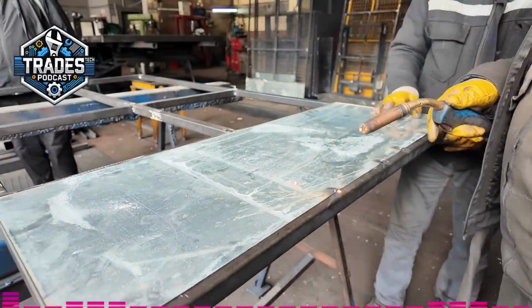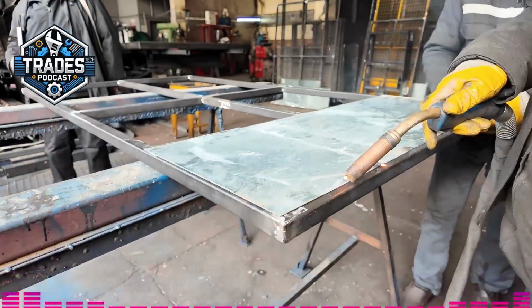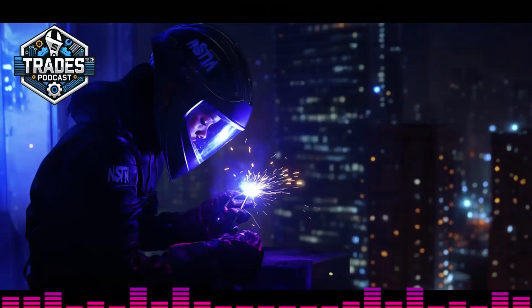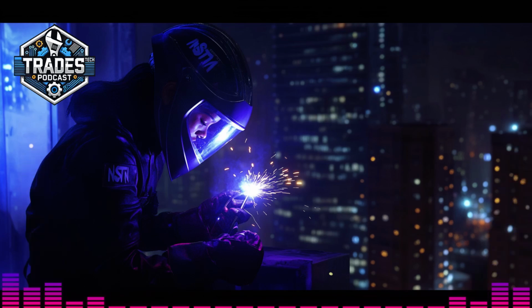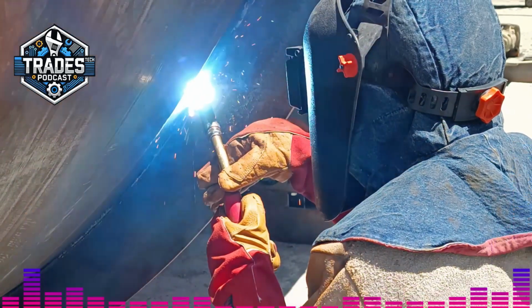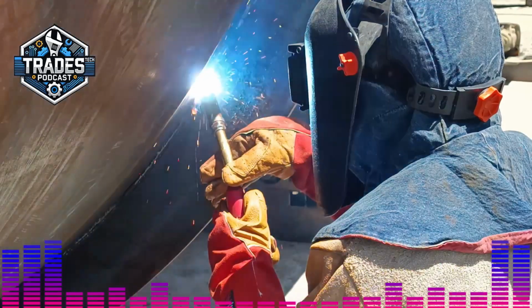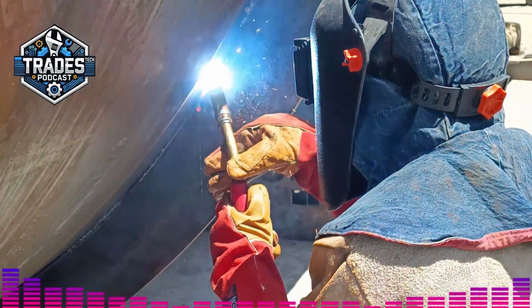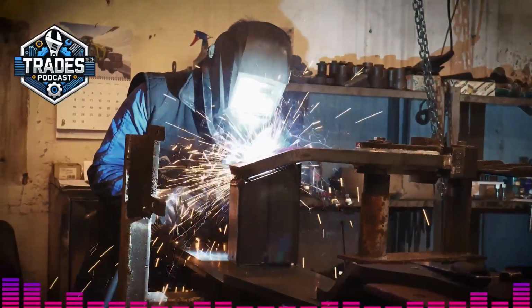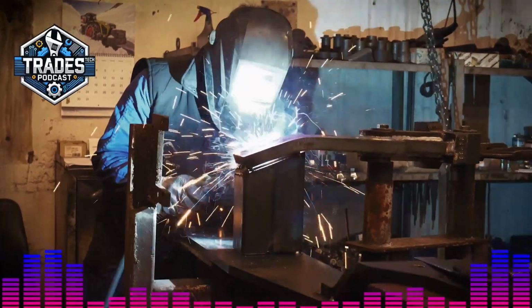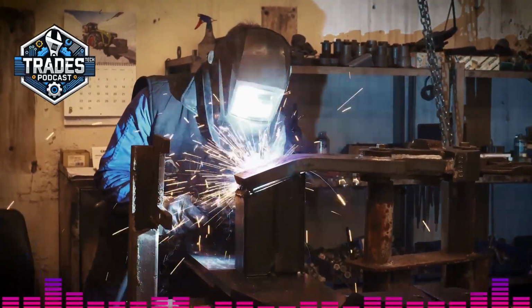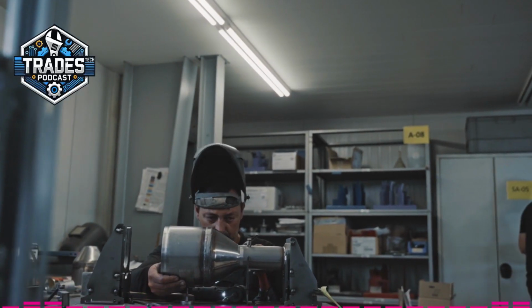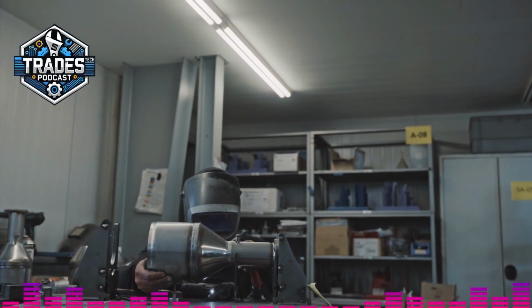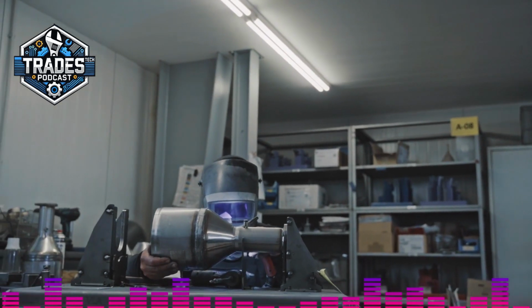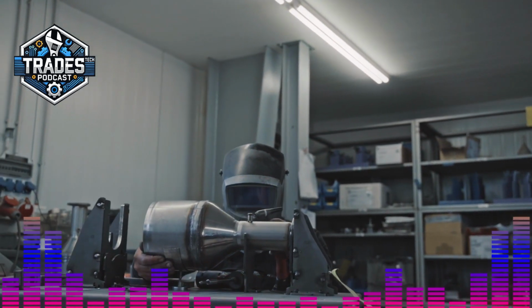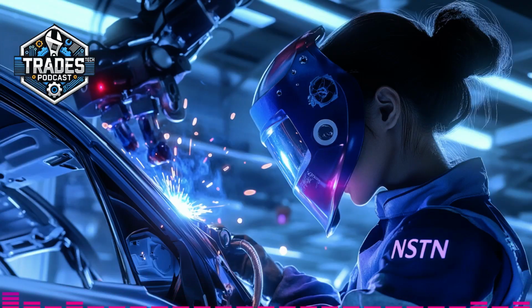Absolutely, Tyler. At its heart, FCAW is an arc welding process that uses a continuously fed tubular electrode wire. The key difference from something like MIG is that this wire has a core filled with flux. Now, this flux does a lot of the heavy lifting. It contains deoxidizers, denitrifiers, and other compounds that help clean the weld and, importantly, can produce a shielding gas and form a protective slag layer over the molten weld pool. There are two primary types based on how that shielding is handled.